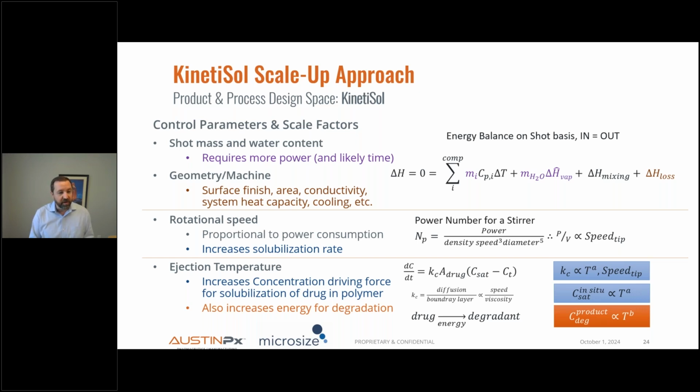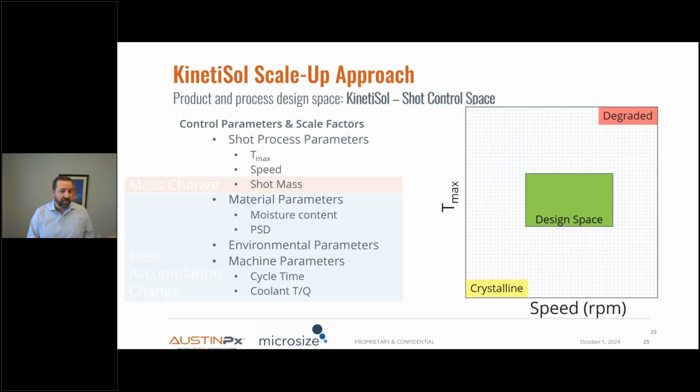But the real part of controlling the process is it's a mixer, and it has a rotational speed. We know that we're going to do a single scale-up event, and we can apply a power number, tip speed relationship to ensure that the RPMs are sufficient to achieve drug dissolution, which is also significantly impacted by the temperature at which we process the material. We know that quite a few melt extrusion and certainly most KinetiSol processes utilize a dissolution process where the process heats up the carrier polymer, it softens and becomes a solvent for the drug, which dissolves into that. And we know that the temperature and the mixing rate or the shear rates can significantly impact the duration required for that. And the counter to this is the longer we heat up any system, the more potential for drug degradation. So we can look at all of these relationships and really sort of simplify this.